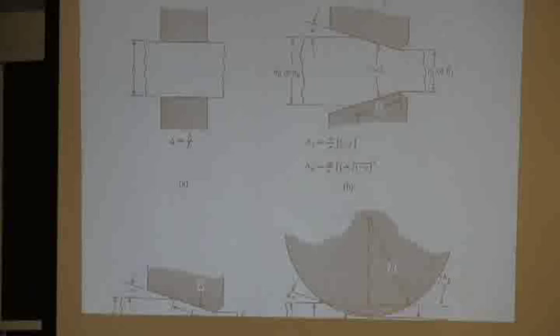This could be wire drawing or strip drawing. There's a delta sub S for strip drawing. If you're drawing a strip of something long and thin, like a piece of paper, it has a lot of depth into the board. Or if it's wire drawing, you're drawing something axisymmetric, with a circular cross section, and you can just do simple geometry. The average height is approximately equal to the length, as he's drawn this. The actual height over here is h1, and here it's h0. The mean height is something in between, and you can calculate what delta is as a function of the reduction ratio of h1 over h0. So you can come up with different delta values.